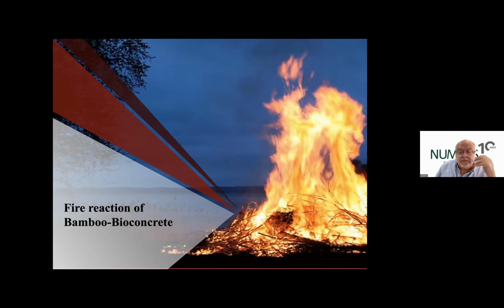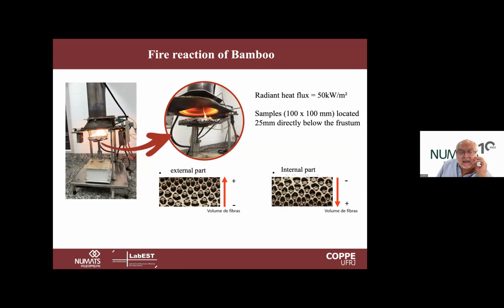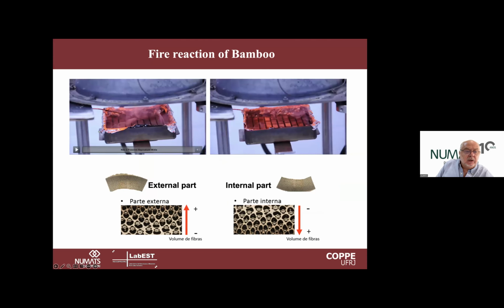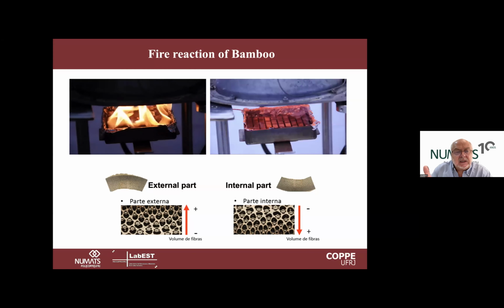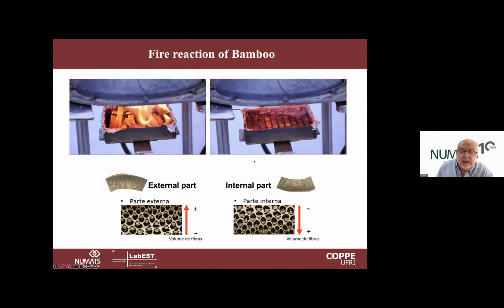So in terms of fire reaction, we use the cone calorimetry test. We did both ways, using also the effect of the bamboo being a functionally graded material. Sometimes we expose the internal part or external part to the radiant flux, and then we see how this material behaves under this heat. So after a certain time, the bamboo ignites, so it gets flammability, both when the inner or the outer part is exposed to the radiant flux.